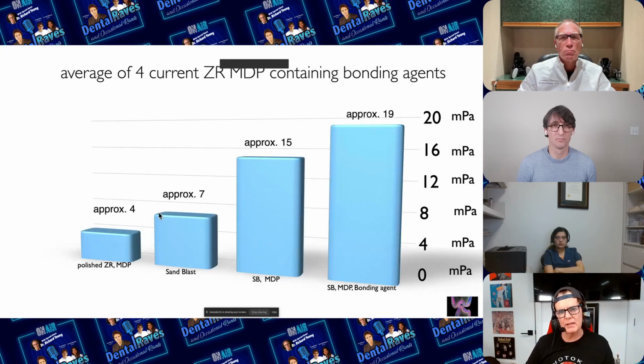So then we sandblasted the surface of zirconia. Just look at the flat surface of zirconia, and then no bonding agent, and then just put the cement on, or put composite on. I looked at the composite cement. They basically behave the same, where we condensed it through a little hole. I'll show you the video in just a second. All right, about 7 megapascals, plus or minus, down to maybe 4 or 3 and up to 10 or 11. So there was a fairly wide range.